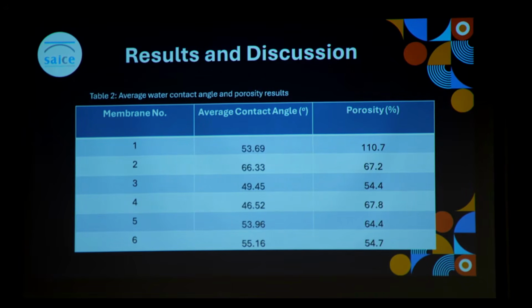However, as seen in membranes 5 and 6, high amounts of the PIL increased the contact angle. This was likely due to structural disturbances in the active layer, where excessive PIL can create voids and expose the more hydrophobic support layer.